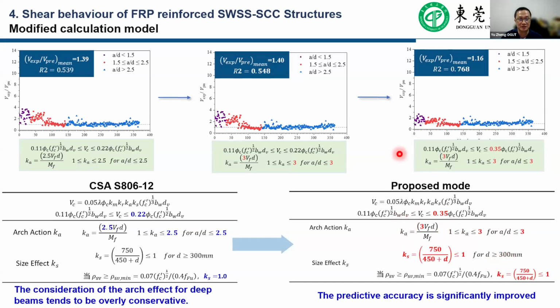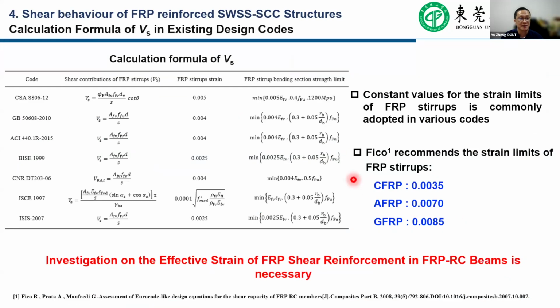After this correct modification, we can find that the accuracy can be improved significantly. Therefore, we can use this model to predict the contribution of the concrete, the self-compacting concrete, to the shear capacity. In the second part of this study, we try to establish an accurate prediction method for the shear capacity contribution from the FRP stirrups.